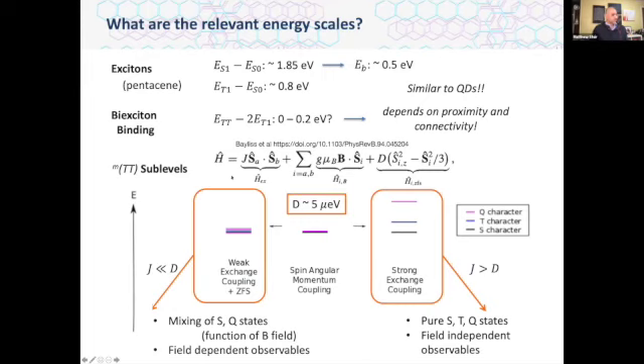Without spending too much time on the Hamiltonian for the triplet pair, the answer to the splitting depends on basically two different energy scales. One would be the interchromophore exchange coupling, and the other one would be the zero field parameter of the individual chromophore. So we have a J term describing how strong the interactions are between two chromophores. We have the zero field splitting D parameter that is characteristic of the chromophore itself.